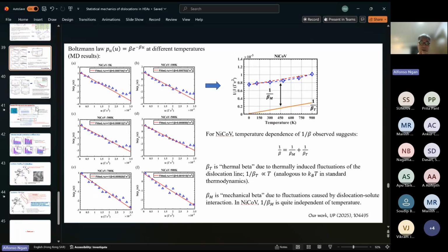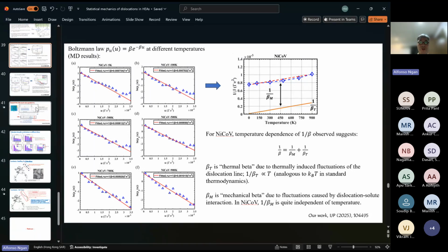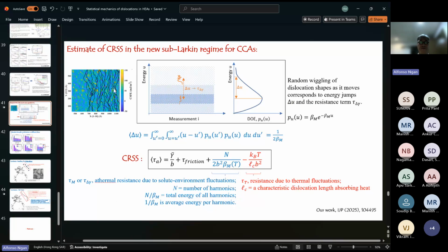I think the distortion obviously would affect both. First of all, I think the higher the distortion, the fluctuation of the fault energy would be higher, especially if you start to have some segregation, which unfortunately hasn't been addressed in our work so far. So it will be up to some future work to look at that. But even for the case that the solutes are not allowed to move around, the positioning or distribution of some of the stronger pinning sites obviously would be inhomogeneous, and therefore we would expect this term in particular to go higher.